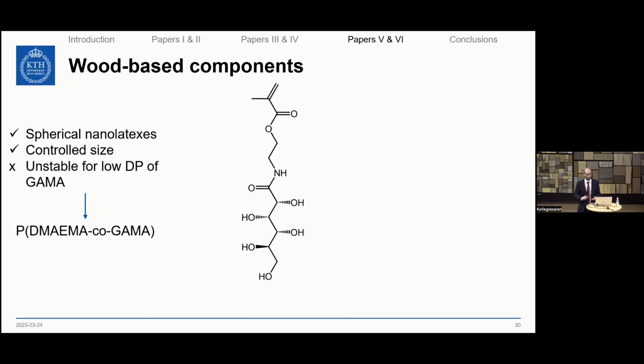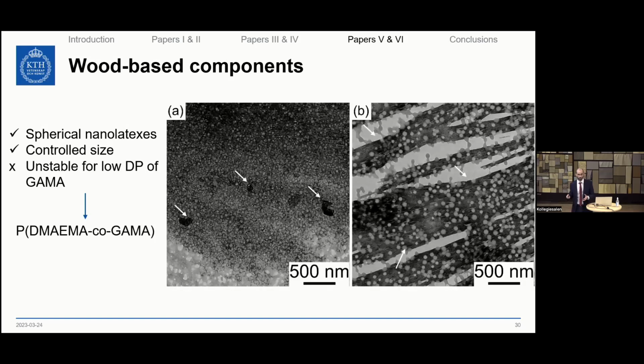In order to showcase quite briefly a potential application of such partially wood-based nanolatexes, we have focused on this great number of hydroxyl groups in the case of GAMA. So we targeted the elimination of copper ions from solutions. Fortunately for us, we were able to have a positive complexation reaction between these partially wood-based nanolatexes and the copper ions in solutions, especially in the case of small nanolatexes, which means that we have a higher surface area and greater number of these hydroxyl groups on that surface.